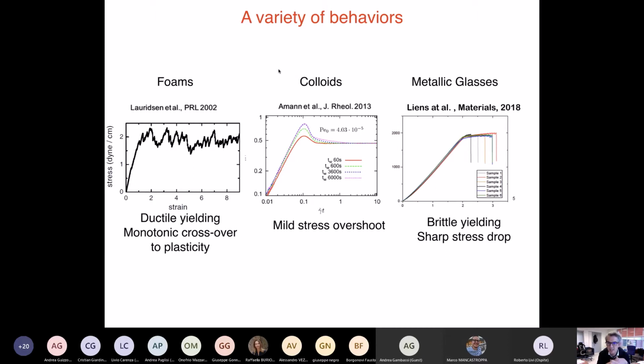In metallic glasses, we are going down in microscopic scale. The microscopic scale for colloids is around 10 to the minus 6 meter, the typical size of a particle. For metallic glasses, we go down to the nanometer. And there you find a very different behavior. In the stress-strain curve, you find that the stress increases.